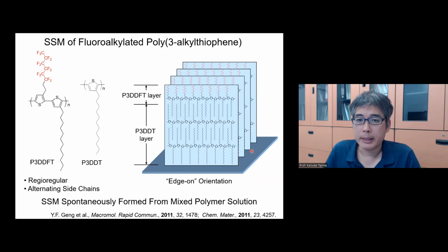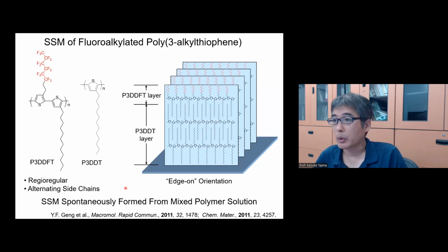We extend this concept to the polymer, polyalkylthiophene in this case, and we design this molecule. This also works as a surfactant, right? The alkyl side chain is partially fluoroalkylated, and the other is an ordinary alkyl chain. And we mix these two polymers together. One is ordinary P3DDT, dodecyl thiophene, and the other is this surfactant. What happened is similar to the previous case. The surface is covered with fluoride chain, and the P3DDT layer is on the bottom. This is a monolayer. And yes, the same surface segregated monolayer spontaneously forms from the mixed polymer solution.